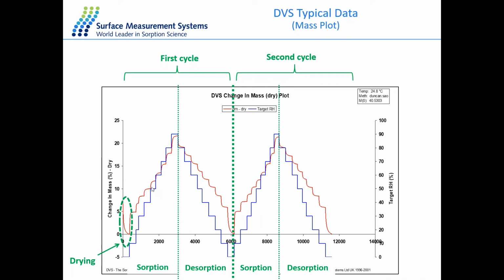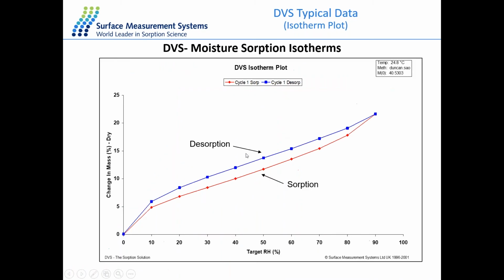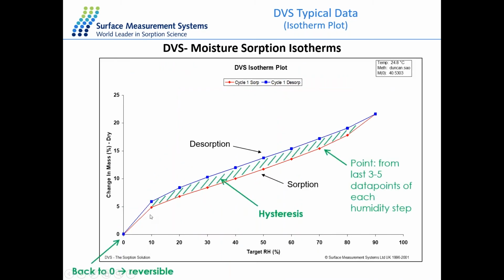And if you take the change of mass at the end of each humidity stage when it's reaching equilibrium and plot it against the relative humidity, then you can get the water isotherm of the sample, with the target relative humidity and the change of mass. So some kind of information you can get from this plot, for example, at 90% RH, the change of mass is about 20%. That means the sample has very good affinity with water. And the red line is for the sorption and the blue line for desorption.